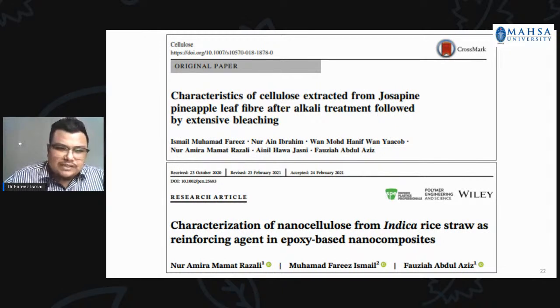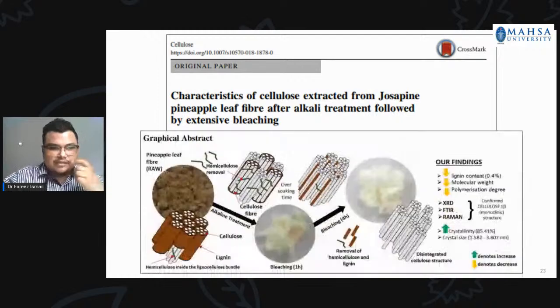In the first one, we isolated the cellulose from the pineapple leaf fiber using alkaline treatment, and it resulted in CNF, cellulose nanofiber. For the second one, we managed to isolate nanocellulose, or crystalline cellulose nanocrystal, using acid hydrolysis. And this is how CNF is produced using the alkaline treatment.